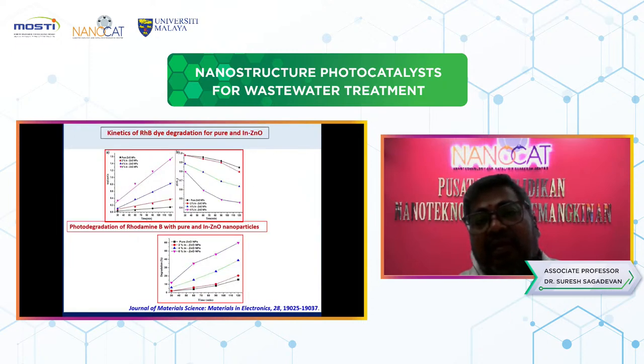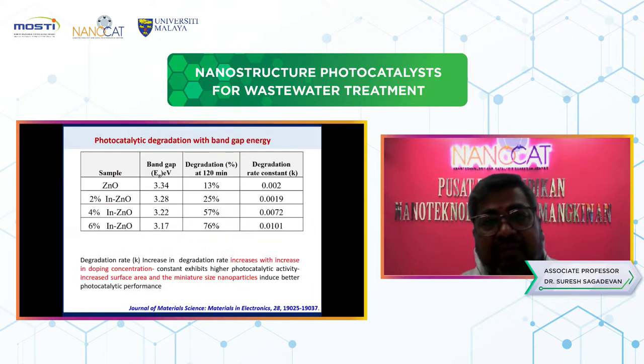Also, we calculated the kinetics of the dye degradation of pure and indium doped zinc oxide, as well as the photo dye degradations, which are represented in the table. You can look here at the values of the table. As the band gap values decrease, the dye degradation also increases. And also, the degradation rate constant increases with increasing doping concentrations.